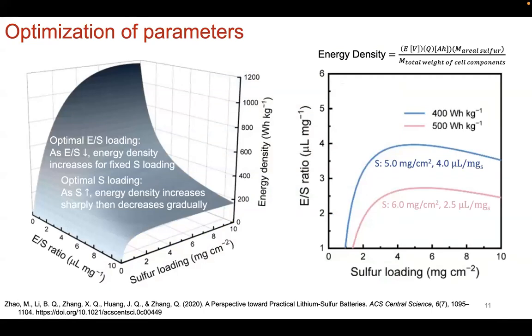So where is the design going? Well, it goes back to what we talked about before, that you want to have a lean operation to maximize the energy density. And to do that, you can decrease the electrolyte to sulfur ratio, so you're not drenching your cell anymore. And for fixed sulfur loading, that does increase energy density. Now, you can also increase the sulfur loading to get higher sulfur utilization as well. But then after a while, it sort of plateaus. So it increases sharply, as you can see here in this model, but then it plateaus and then sort of decreases, which is not so obvious from this angle.